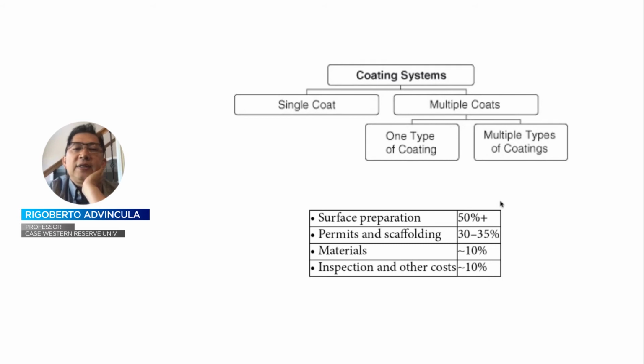On the other hand, a single coat system could be a proposition for decreasing the cost. But in general, a typical coating project should involve a minimum of about 50% surface preparation. Why am I emphasizing this? Well, surface preparation probably is one of the biggest sources of failure in any coating job. If you don't prepare the surface very well, over time, the coating you added will delaminate or degrade, and therefore you have to redo everything again.